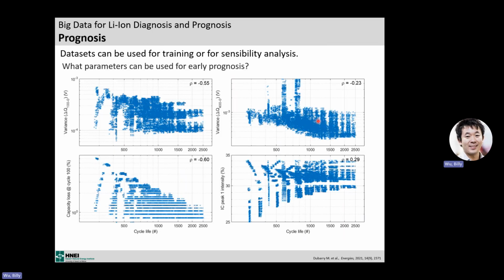Now, we can do the same thing for prognosis. And remember what I said about the Stanford paper. Again, great paper. I'm not saying it's a bad paper. It's a really good paper. But they said in their paper that the variance at cycle 100 is an extremely good indicator of state of health. And I think they give a correlation coefficient of around 0.9. Well, when you do it on a varied data set, the correlation is not that good. The correlation is actually worse than just looking at capacity loss.